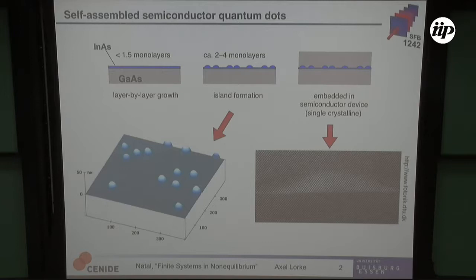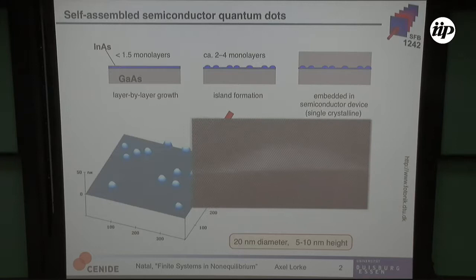This is shown here, where you can see in white the rough outline of the indium arsenide and in darker the gallium arsenide around. They have a diameter of about 20 nanometers in XY direction and a height of 5 to 10 nanometers, and what you can see here is how well preserved the underlying atomic lattice is. And this will be the last picture that I show you that has anything to do with an atomic lattice. I will try to move away a little bit from